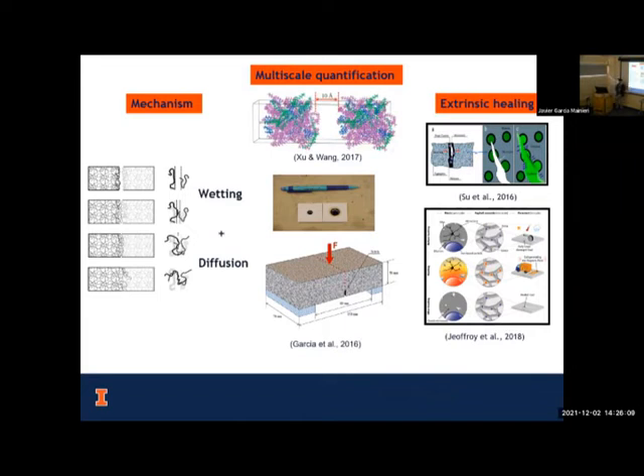And this is basically where you add something that conducts heat as an aggregate to the asphalt specimen. So you can add some steel slag, for example. Then you use induction to heat the pavement, and that steel slag raises the temperature of the asphalt binder. And at higher temperatures, again, that healing capacity is restored.